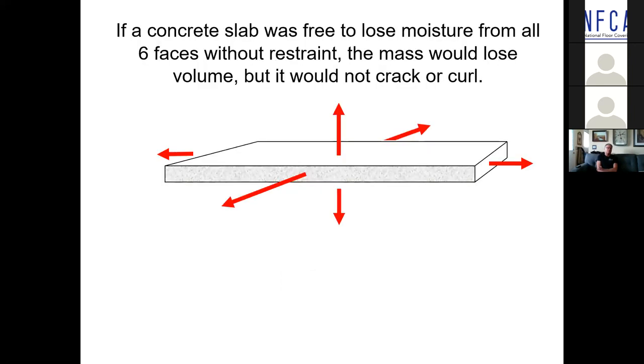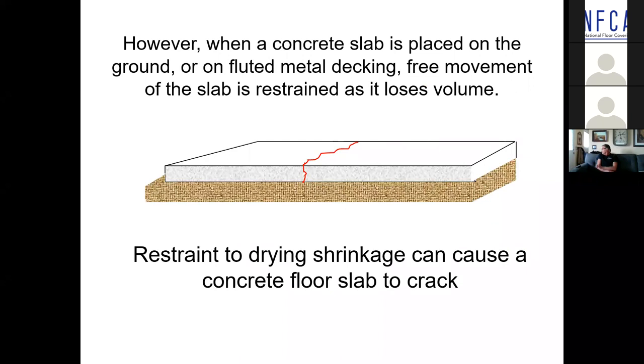Now, if you had a concrete slab that you could levitate into space such that it was free to lose moisture from all six sides, there would be no internal stresses, if you will, shrinkage stresses that would result in cracking. But because we place these slabs on the ground or on deck, there's the issue of frictional restraint. Even if we're on plastic, ultimately there's a measure of frictional restraint that can lead to a crack.